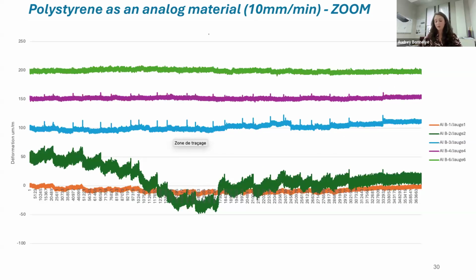And we see that if we try to go faster, so 10 millimeter per minute, so 10 times faster, we observe a very different behavior. And actually, we could even hear it, and we could hear some noise when we were moving much faster.